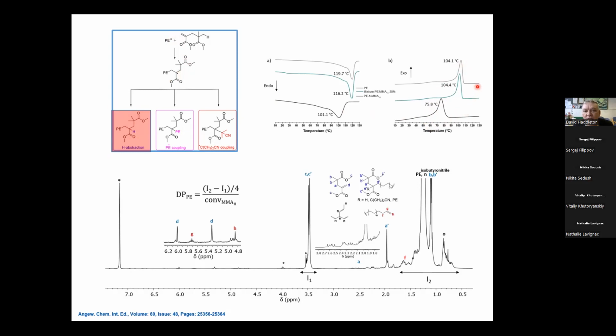So what we've got here is polyethylene with a melting temperature of 104, and then we mix polyethylene with the PMMA macromonomer without doing any chemistry, and we see the melting temperature of the polyethylene stays the same, whereas for the product we get from the two, the melting point changes quite a lot. And the same in this experiment here, so we see the Tg change as well as the melting point.